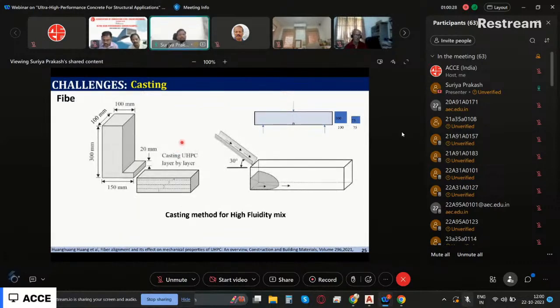Now, what we can do is a casting method for highly fluid mixes. With this kind of trough at a 30-degree angle, we can cast and let the concrete flow from one side to another side. In this way, in a beam, we can always make sure that the majority of the fibers are oriented in the horizontal direction. That will help in arresting the crack. Okay, these are some of the challenges.